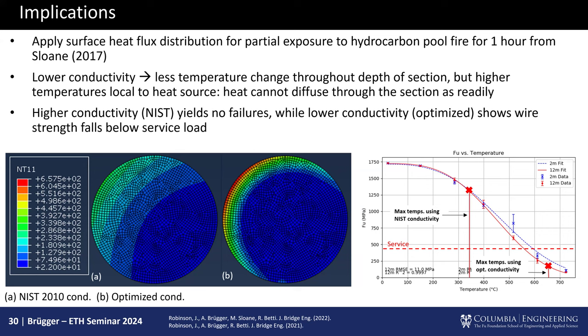Instead of a surface temperature causing minor damage, we now have a surface temperature where wires are actually breaking. We tested this in the lab and it literally peels like an onion. If you take a strand under tension, you locally overheat the wires, they creep, plastically deform, and break — the wound opens up. In a large array, that deformation may not actually cause failure; it may just cause redistribution of stress to the intact wires.